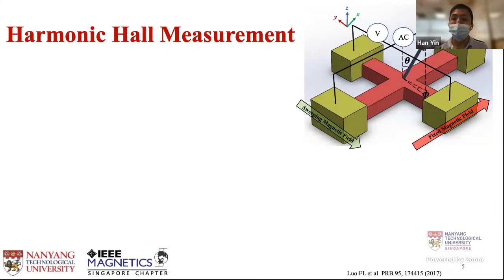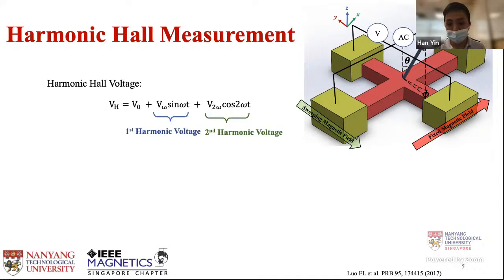In our technique, we utilize a DC bias harmonic Hall measurement to quantify the spin accumulation. Before diving into our technique, do allow me to give a brief introduction on the conventional harmonic Hall technique. The harmonic Hall technique is basically the measurement of the perturbation of voltage under SOT in an AC current and magnetic field. So the Hall voltage can be described by this equation over here, where the sine omega t term is the first harmonic and the cosine 2 omega t term is the second harmonic.